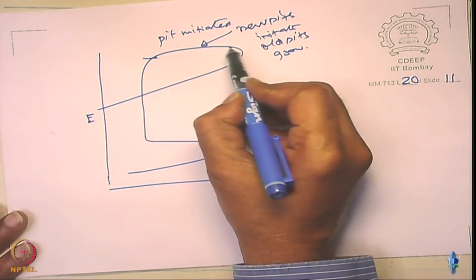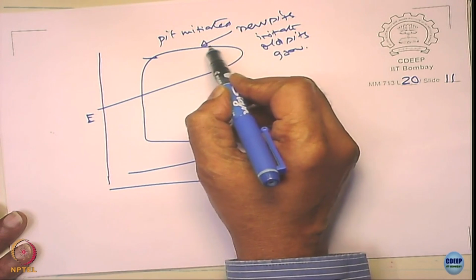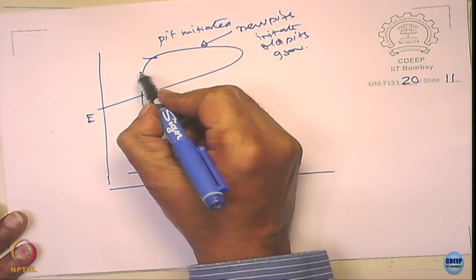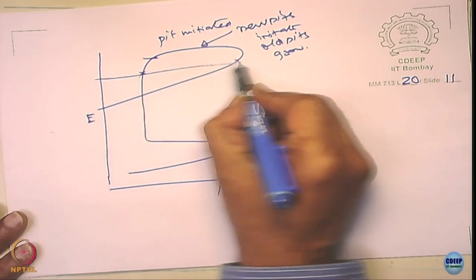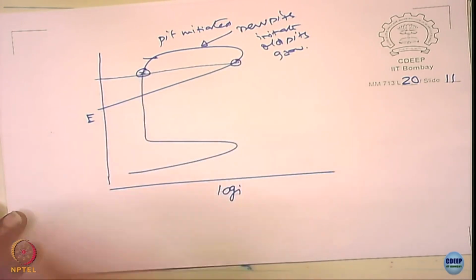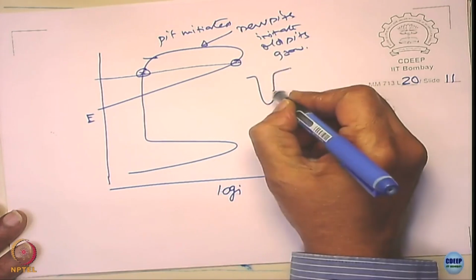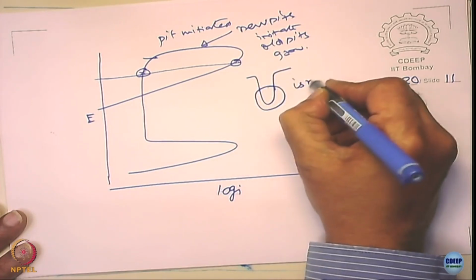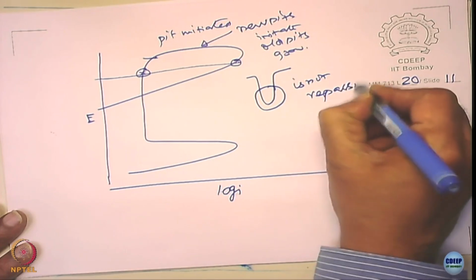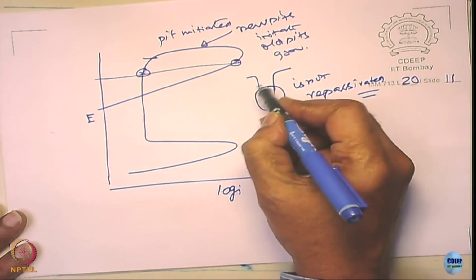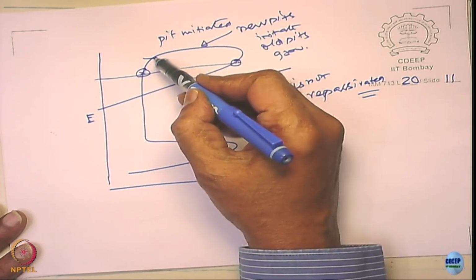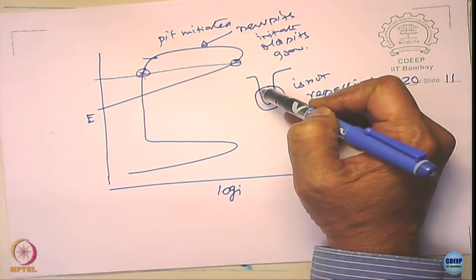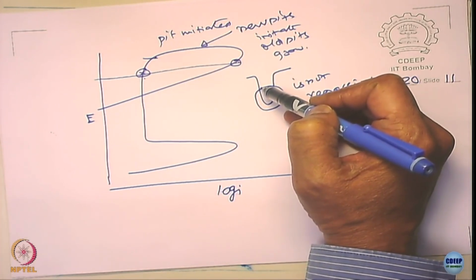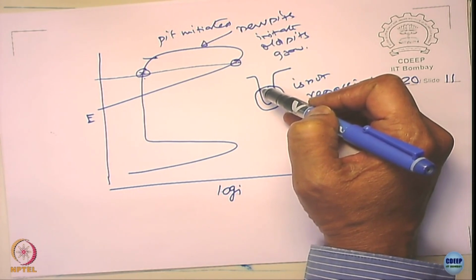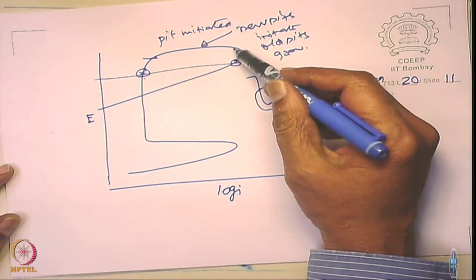Now what is happening now when you reverse this current here? Please see this. It is not following the same path. Rather, what happens now? The reverse current is higher than the forward current, right? Why does it happen? It happens because when you have a pit formed here, this pit is not repassivated. The pit continues to corrode. Even though you are bringing the potential below the pit, the pit continues to grow because the pit is now seeing a higher chloride ions, it is seeing a higher amount of H plus ions, and the film is totally damaged, it is not healing at all.